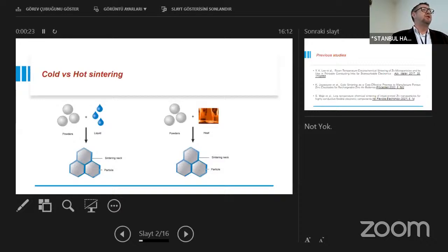Everyone who heard about powder metallurgy knows what sintering is. It's a very simple thing: we heat the sample or part in order to make metallurgical bonds between the particles involved. If these particles are not bonded metallurgically, their mechanical properties are almost inexistent. For the beginning of powder metallurgy, this sintering was done by using heat to improve the diffusion of atoms from mostly the particle surface to the sintering neck. It's very nice, very well working, but you need high temperatures - about 0.7, 0.8 of the melting point of the main component.